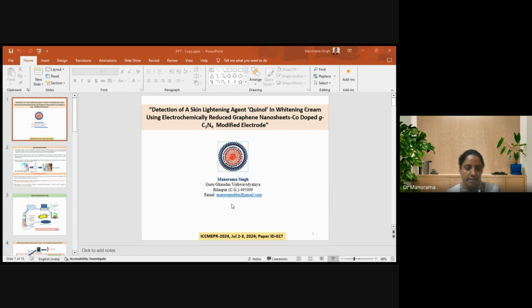We make a thin film on the working electrode, that is a glassy carbon electrode, and then we use one reference electrode, which is a silver/silver chloride electrode, and one counter electrode, that is a platinum bar electrode, and a three-electrode system is there. We take the sample here, in which we have to analyze the analyte, and then we connect it to the potentiostat, and it is totally software-based.